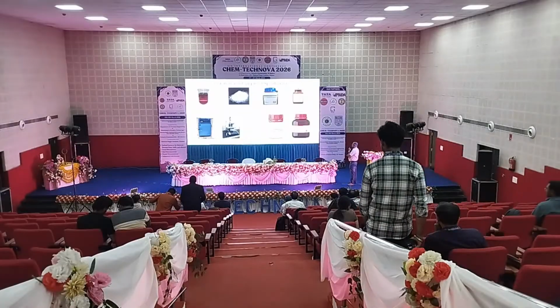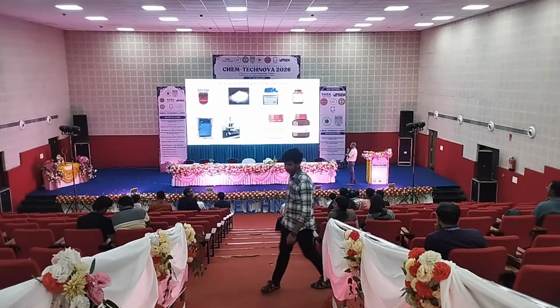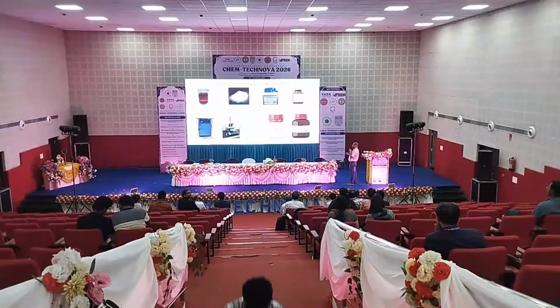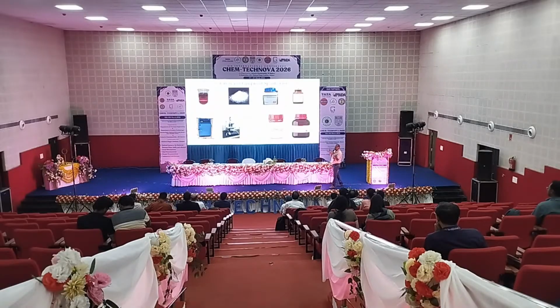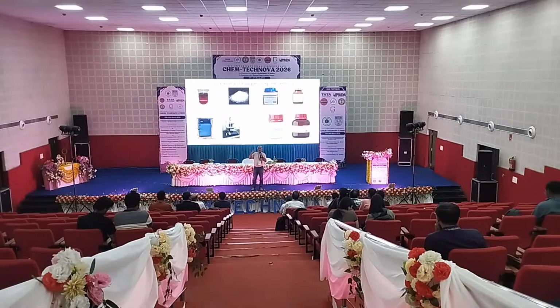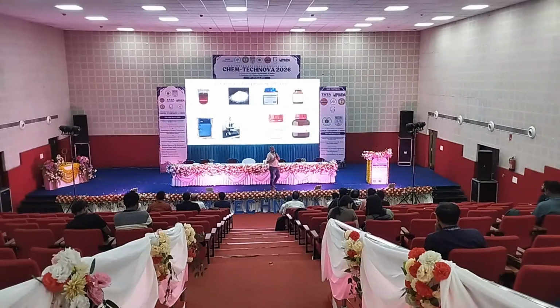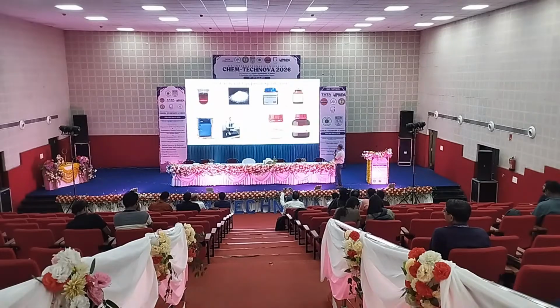So here in this work, the composite thermal shield work, we used phenolic resin, nanosilica, and boron nitride. Nanosilica will give you structural integrity along with thermal stability. Boron nitride will also withstand more than 2000 degrees centigrade very easily. So both are proven candidates which will be applicable for high temperature applications.